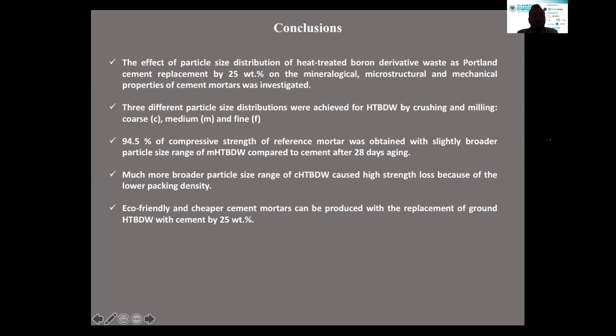So as a conclusion, we investigated the effect of the particle size distribution of heat-treated boron derivative waste on the properties of cement mortars. We used it as a replacement at 25 weight percentage. We achieved heat-treated wastes with 3 different particle size distributions. According to the obtained data, 94.5% of the compressive strength of the reference mortar was obtained with the slightly broader particle size range of the medium heat-treated boron derivative waste.